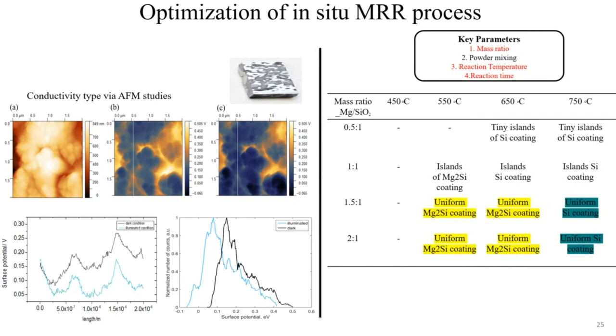So in order to address the challenges with the first attempt, which had to do with non-uniformity of the silicon coating, we did a kinetic study of the in-situ magnesiothermic reduction on the silicon wafer, and this table presents the in-situ results of the kinetic study, and it can be seen that a mass ratio of magnesium to silica around 1.5 to 1 and 2 to 1 at temperatures of 750 yielded uniform silicon coatings. And interestingly, lower temperatures yielded uniform magnesium silicide coatings, of course with impurities of magnesium oxide. And the surface of these coatings can be seen from the images below.